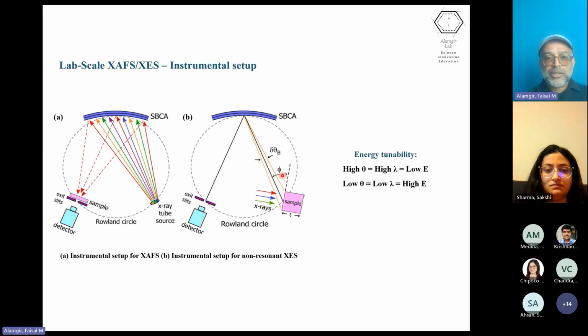based instrument, with a clever design, allows us to do both X-ray absorption and emission. So essentially, the sample, detector, and X-ray source, as well as the monochromator crystal, all sit on the arc on the circumference of a so-called Rowland circle, and by doing so, we are able to take emerging X-rays from either the sample or from the X-ray tube, and do Bragg diffraction using the crystal while also refocusing them back to an image point that images the source back. So in other words, we recollect the large solid angle of emission that's hitting the crystal.